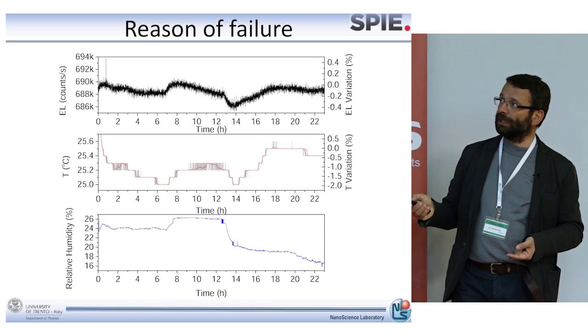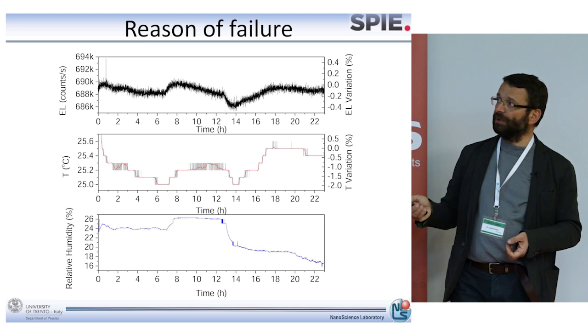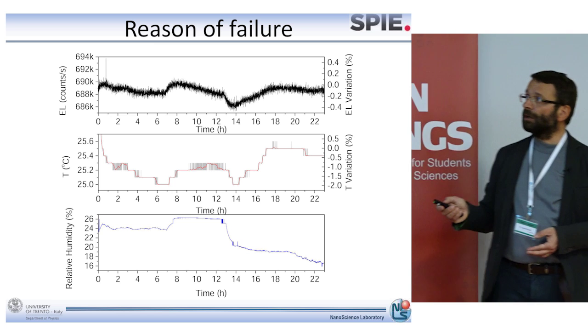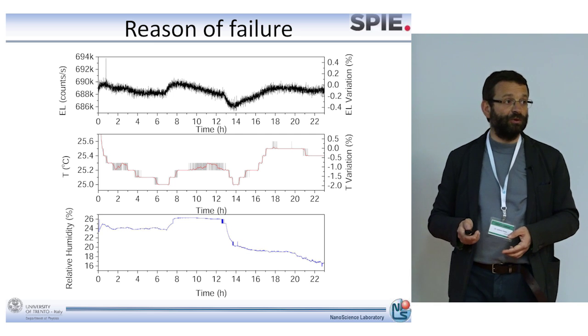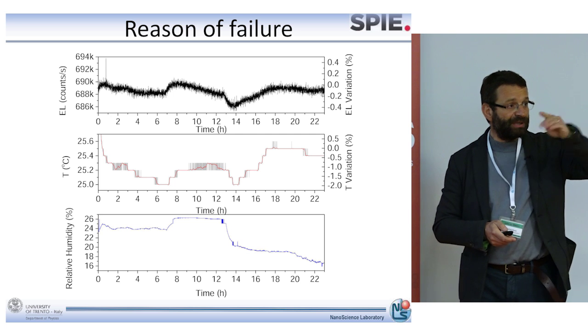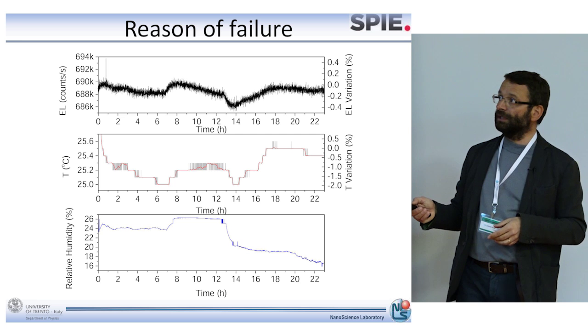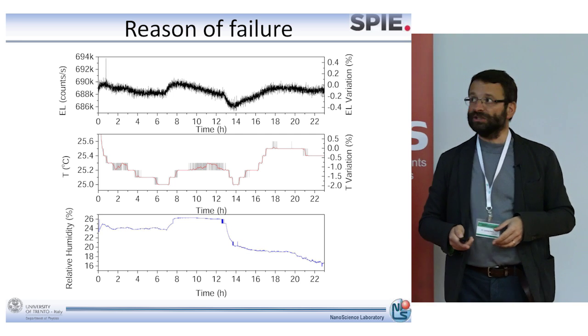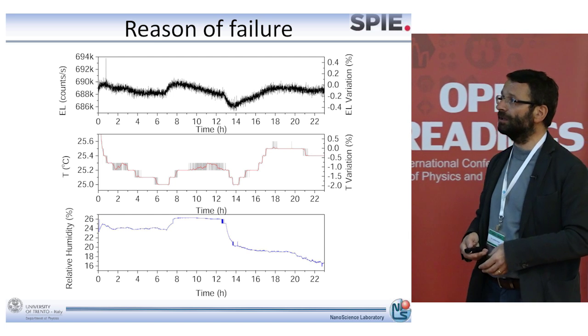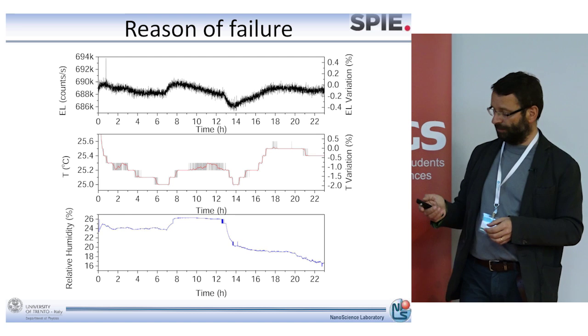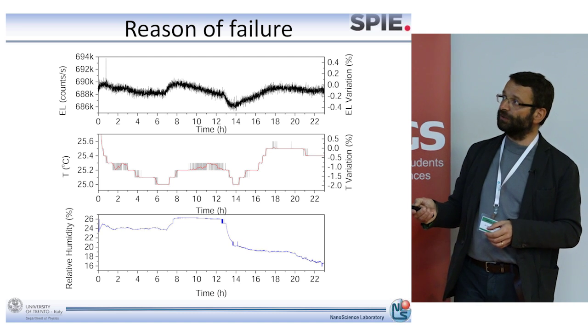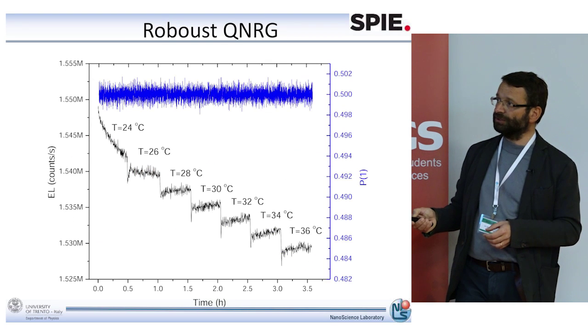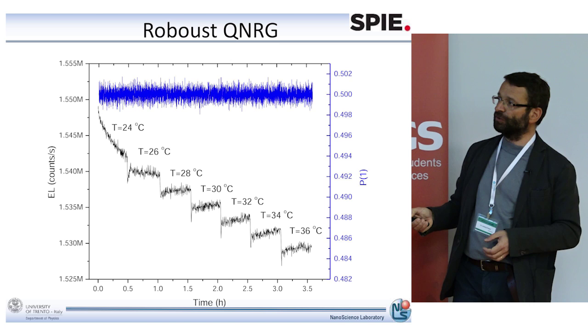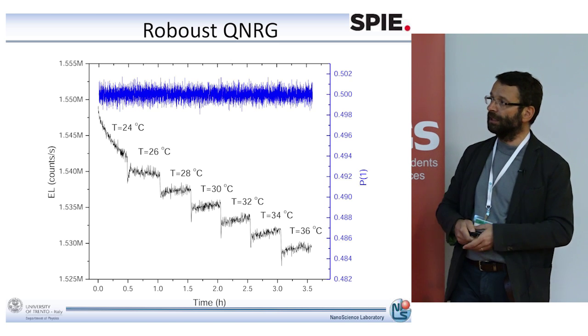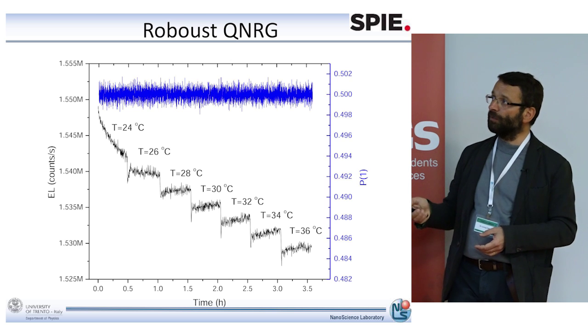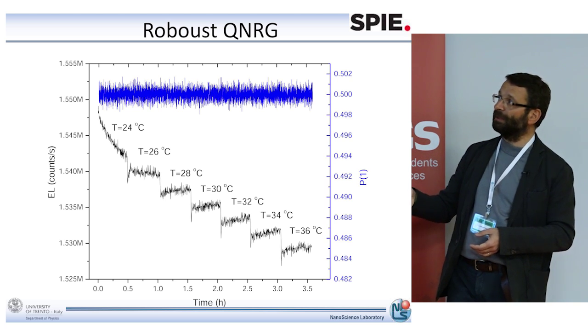And so here is the electroluminescence as a function of time for our LED over a day. And what you see is that the variation in the electroluminescence is in the few per mil. Very stable, few per mil, but not yet enough for our quantum random numbers. And the reason is the variation of the temperature in the room. So we did some processing, we did some tricks in order to extract the photons in a proper way, and this is the result. So this is a scan in the temperature. You see that when you change the temperature of the photon source, you get a lower electroluminescence efficiency. But in the way we use to extract the data, we see that the probability is still 50%.